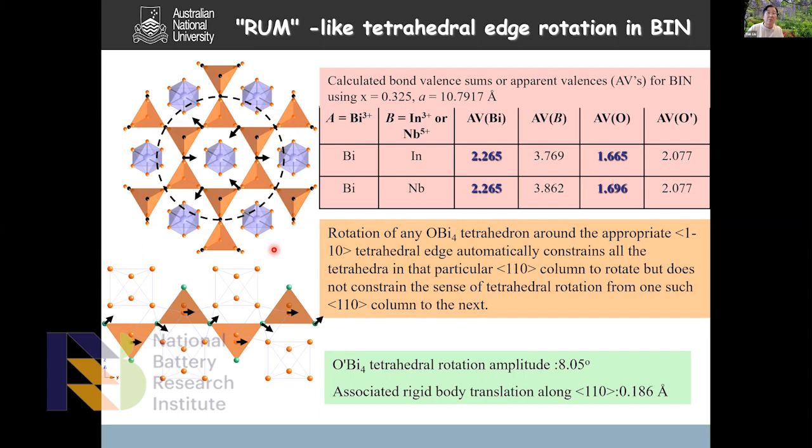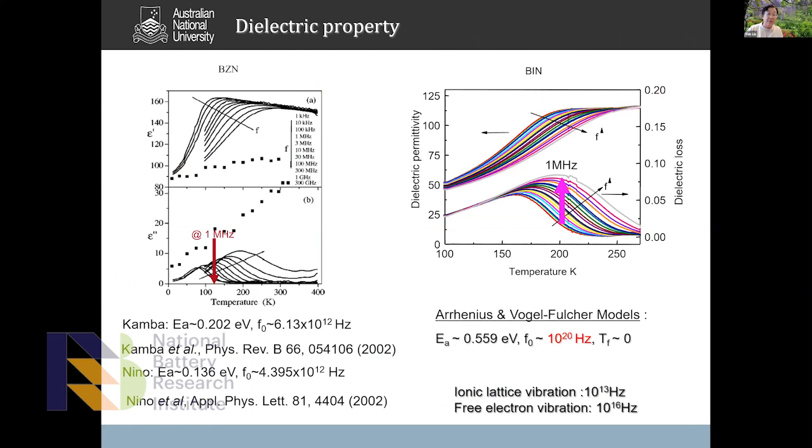So yeah, if we look at this different direction, you can see here you get octahedral tilting along this direction. That gives you net dipoles that make a contribution to the relaxation of the dielectric property we saw here. But this one, I didn't go further. What happened is this one has nothing to do with your local structure; the relaxation is because of the oxygen vacancy. I didn't talk about that because today we are focusing on the structure. Okay, so that explains that.